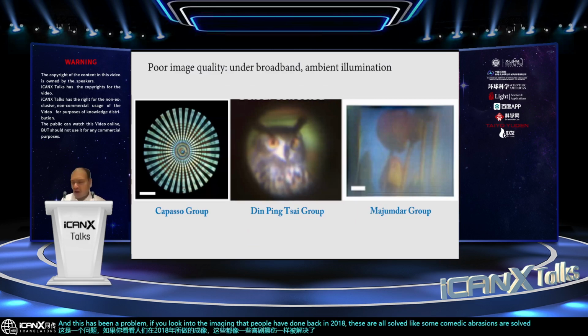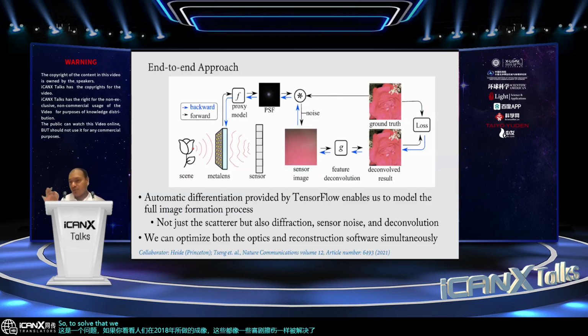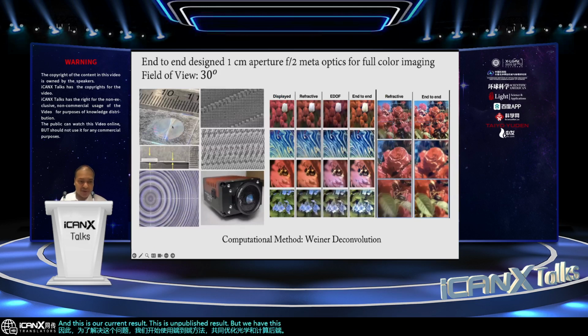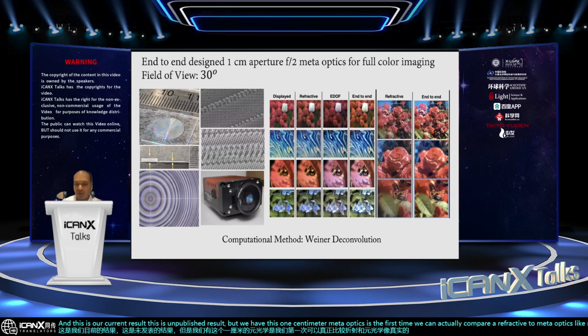So to solve that, we started doing this end-to-end approach that co-optimized the optics and computational backend. And this is our current result. This is an unpublished result, but we have this 1 centimeter meta-optics. This is the first time we can actually compare a refractive to meta-optics, a real apples to apples comparison. I can get a 1 centimeter refractive with the same F number, and we compare them. We can put both of them directly on the camera. And this is the displayed result.